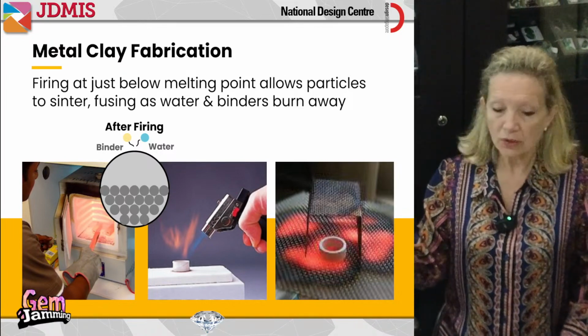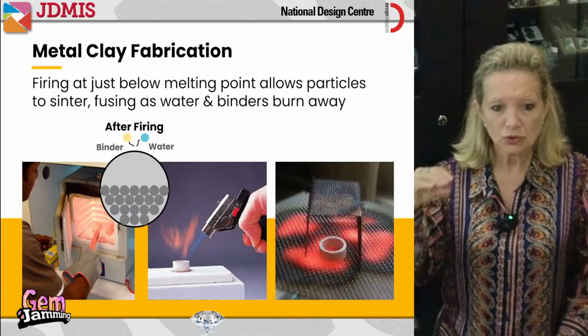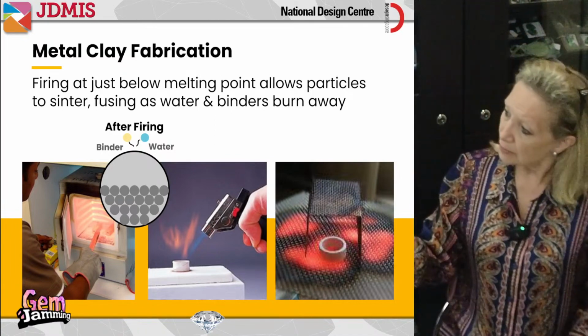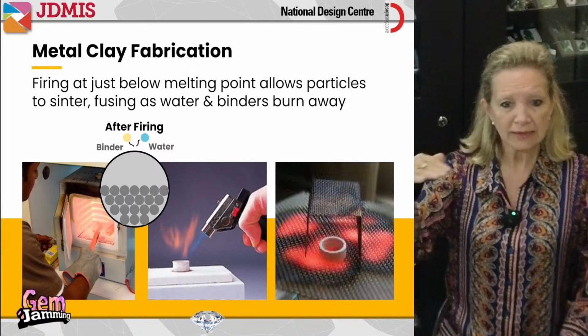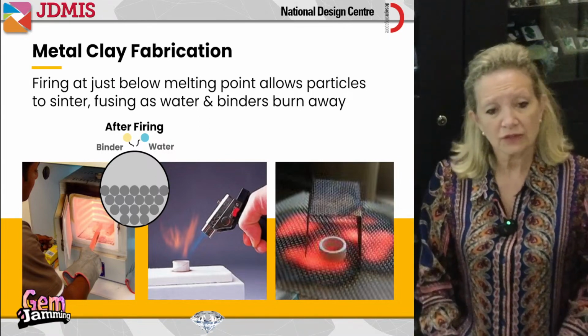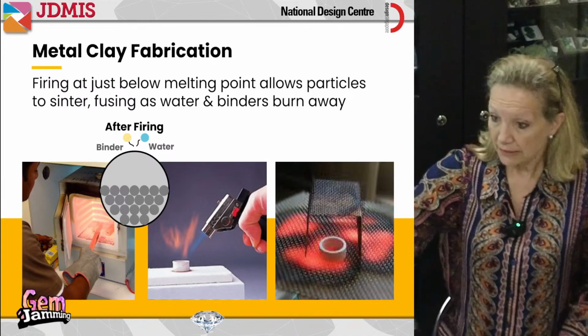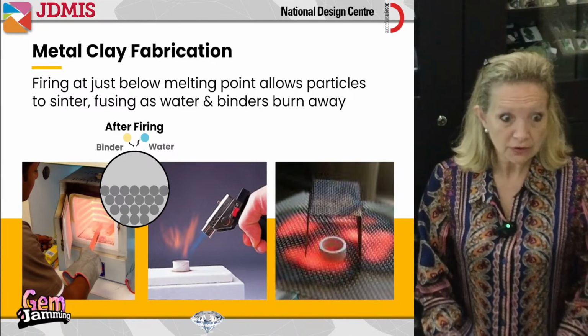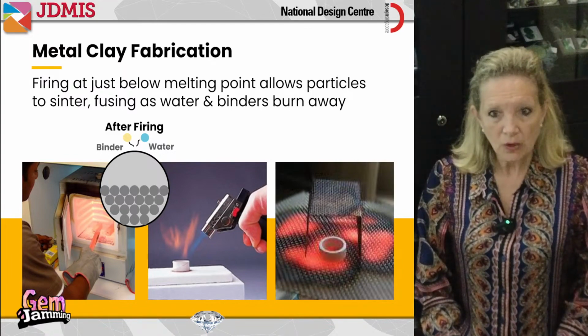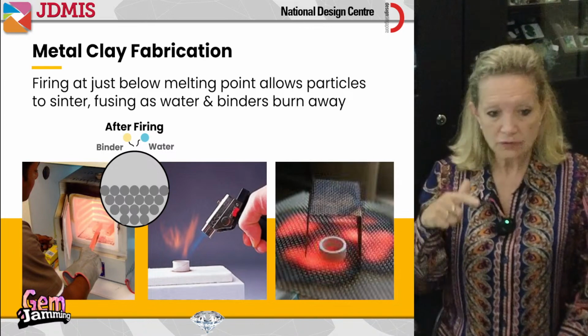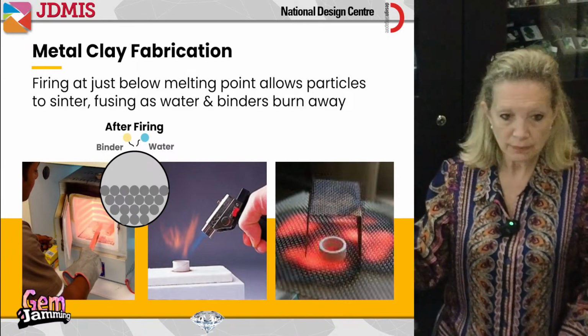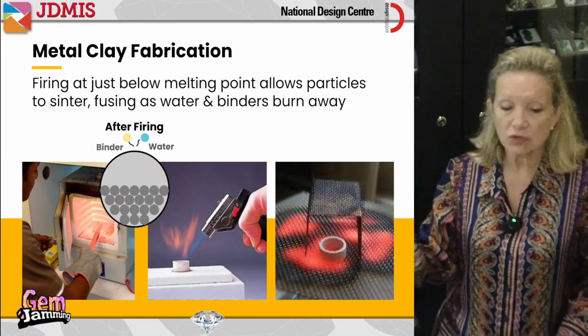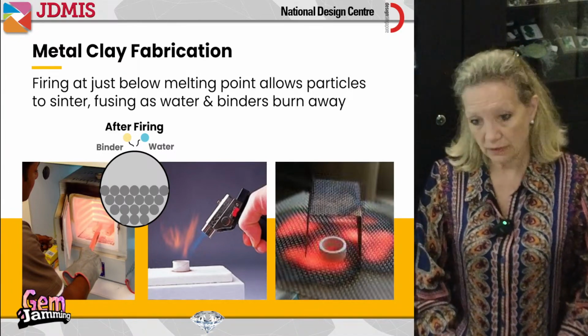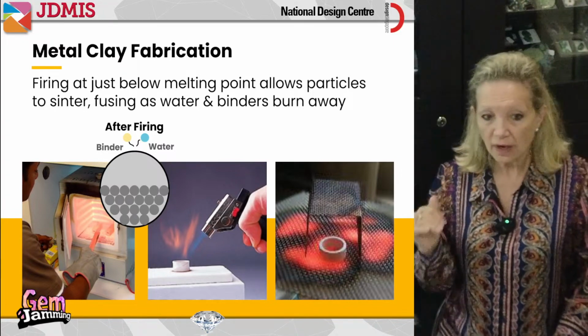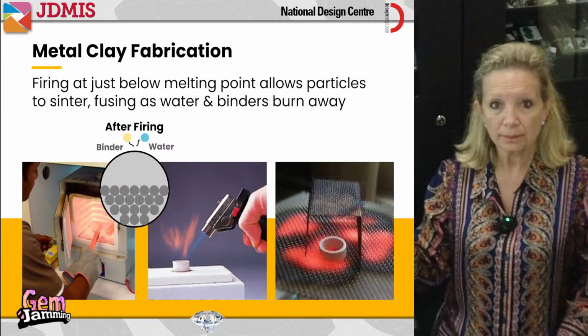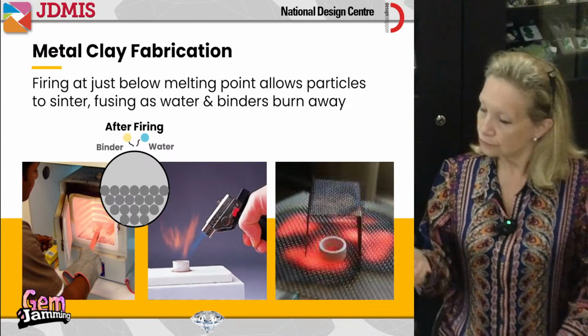But if you're going to sinter it at the lowest temperature, then you should leave it for longer. So for example, if I'm doing it in a kiln, I might plan to do it at 800 degrees for 15-20 minutes. If I'm doing it with my torch, it goes to about 1,300 degrees, so I would be a little bit more hesitant, and I would only leave it for about 2 minutes with a torch. And that would sinter it perfectly well because of the heat. But if I'm doing it on my gas stove, then I would leave it for at least 10 minutes. So different temperatures, different timings, and I would definitely, Bella, use full on your gas stove and leave it for 10 minutes.